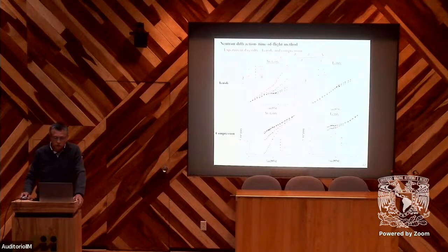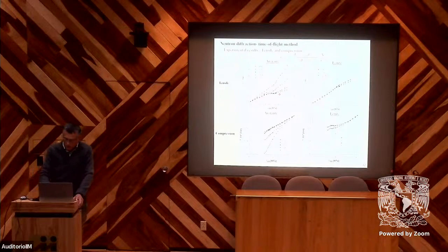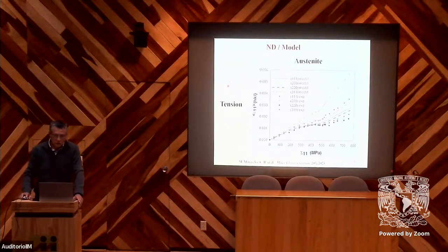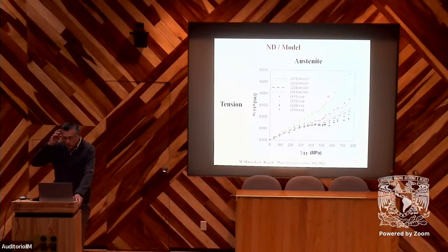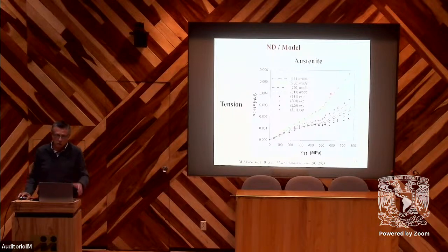You can see the evolution for each reflection. We can observe the anisotropy effect. For example, if we look at just one case, the tensile test for austenite, we can see the main reflections here. We have the effect of the anisotropy of the crystal, and afterwards we can also observe the anisotropy in the plastic deformation of the phase. Now, if we compare the diffraction data and our model, we can obtain different parameters, and we can see that we have an acceptable agreement between the two.